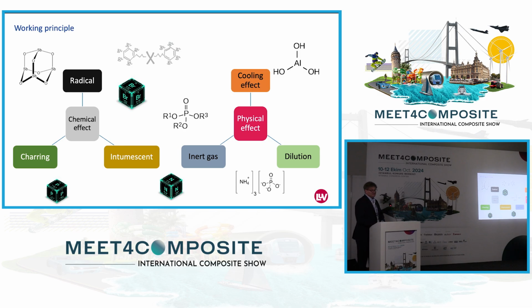And the best effect, well known, is from halogens. Halogens build up radicals and have the best effect in terms of flame retardancy, in combination with antimony trioxide, for example. But nobody likes halogens anymore since a couple of years, because you have also a strong side effect by building dioxins and also by building hydrochloric acid gas, which is toxic.